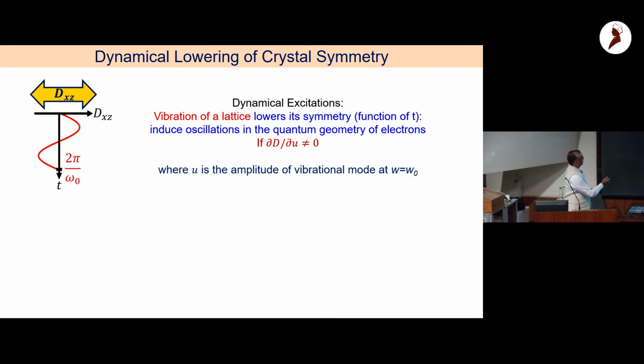So what we proposed is the Berry curvature dipole can oscillate in time with the frequency of your dynamical excitation, omega naught. These can be vibrations, for example, and a vibration will induce a Berry curvature dipole, provided the first derivative of the Berry curvature dipole with respect to vibrational amplitude is non-zero. Just to remind you, the Raman effect is where the first derivative of polarizability with respect to vibration is non-zero. Here we are proposing the Berry curvature dipole. Like in infrared spectroscopy, if the electric dipole's first derivative with respect to the phonon is non-zero, the phonon is polar and IR active. Here it's the topological or geometric feature of a phonon. So this defines the selection rule for the spectroscopy that we are introducing now.